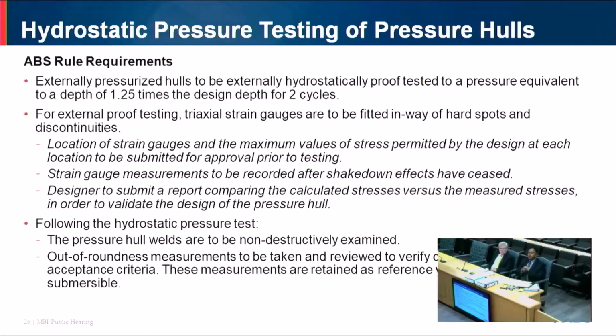So in new construction pressure hulls, you will notice localized areas of high stresses on the hull. So when you pressure cycle the hull above its design pressure, what happens is these localized areas of high stresses start deforming, okay? So you'll have localized deformation and then strain hardening occurs. Once the strain hardening occurs, no further deformation of the hull occurs plastically. All the deformation is in the elastic region, okay? So that is when the shakedown effects cease.